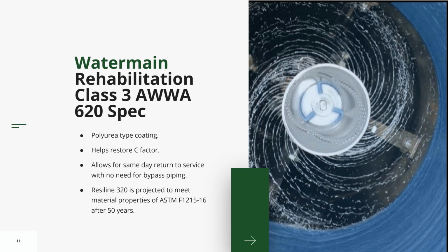It does have the ability to span holes and to span leaks in the pipe. And what it's doing is it's providing the ability for the pipe to now hold water again. It also helps us in the case of water pressure pipes. Of course, it's a C factor, not an N factor, which is the friction factor of water going through the pipe. So it does help to restore your friction factor because, of course, in water pipes, we often get a lot of materials building up on the inside and a corrosion, and this stops that happening. You can do this in one day.